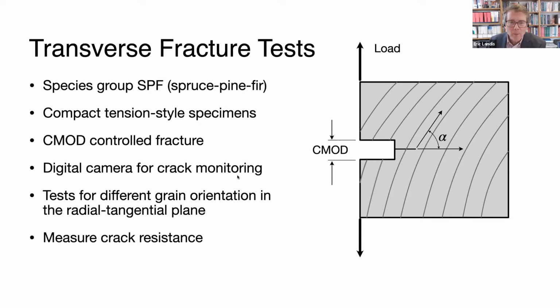Then as part of the experimental system, we have a digital camera for monitoring the crack growth. And we use different specimens with different grain orientation. The way we're defining the grain orientation is an angle alpha, which is the angle between the horizontal plane of the crack and the tangential direction. So if we have an alpha of 0, that means we are propagating a crack in the tangential direction. If we have an alpha of 90 degrees, the crack is going to be propagating in the radial direction.